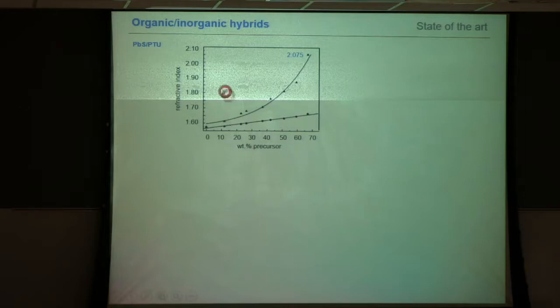Clearly, you can reach higher refractive index. So you see here nicely, because of the high refractive index of the lead sulfide, when you add more lead sulfide in, you get to a decent refractive index for an organic-based material, the organic meaning the polythiourethane, PTU.